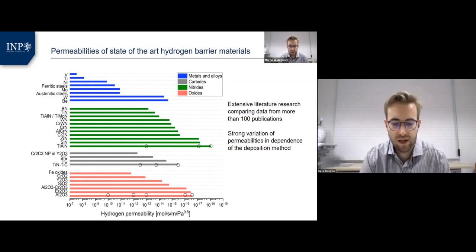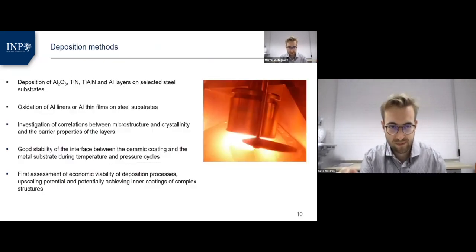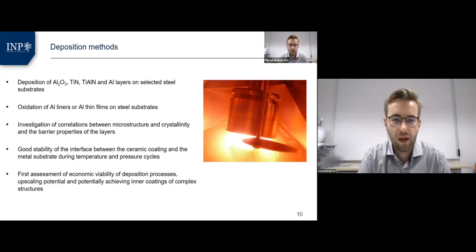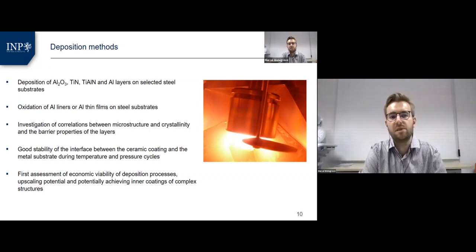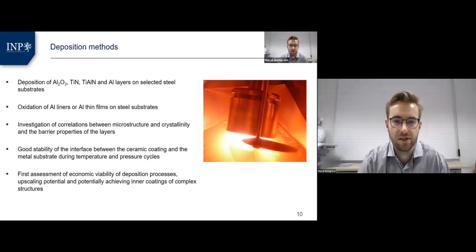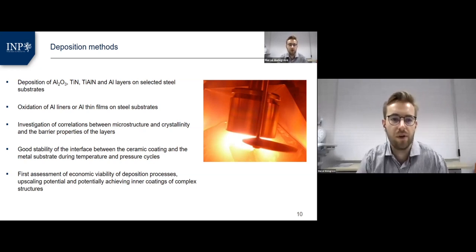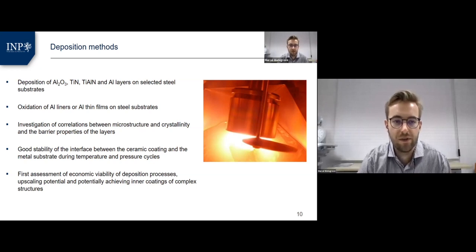However, we found a strong variation of literature values for permeabilities, depending on the deposition methods and also on the methods used for measuring permeability. And this shows that the development and the optimization of coatings is really key to obtain high performance barrier coatings. So our further steps after the deposition of these coatings is to investigate the correlations between the microstructure and crystallinity of our barriers, and to correlate these with the barrier properties.